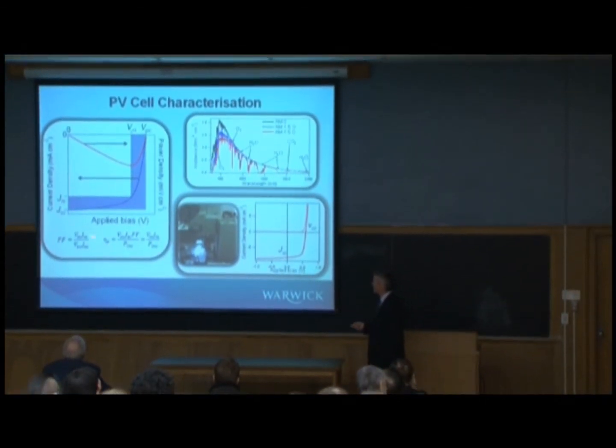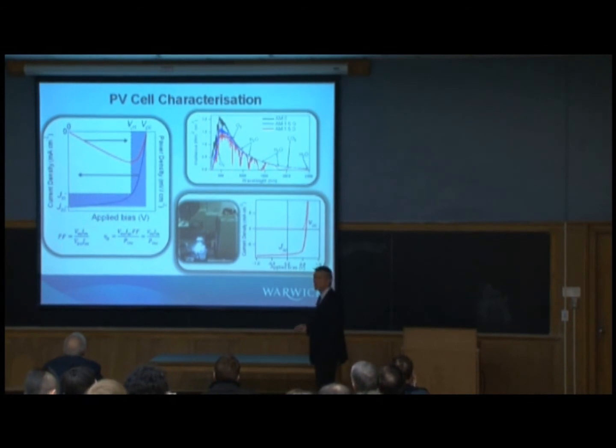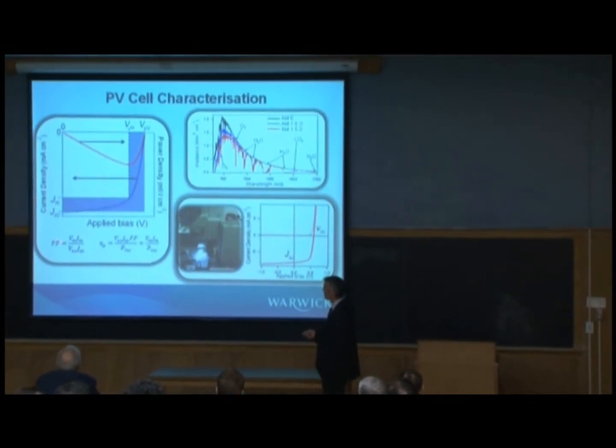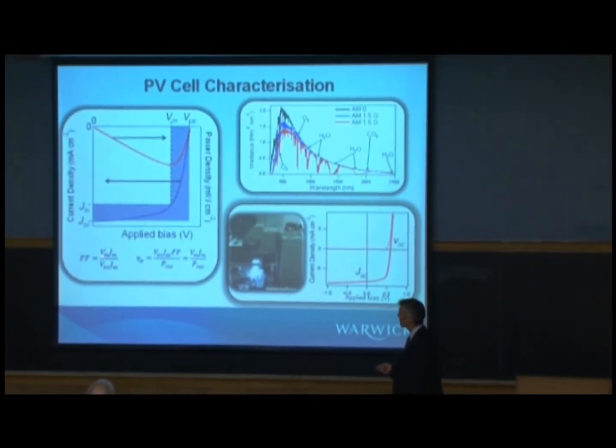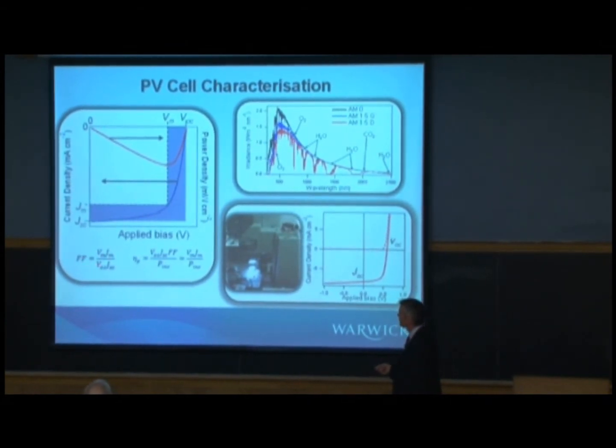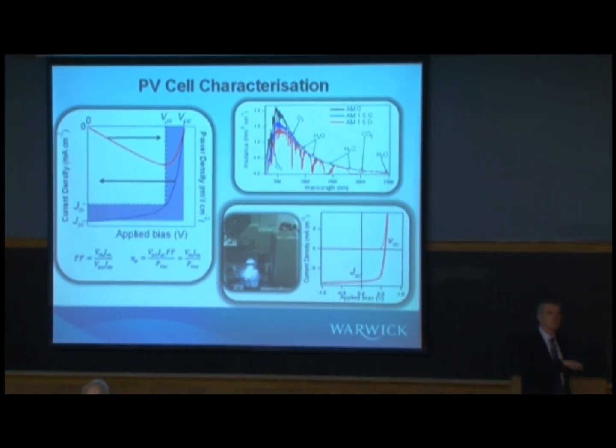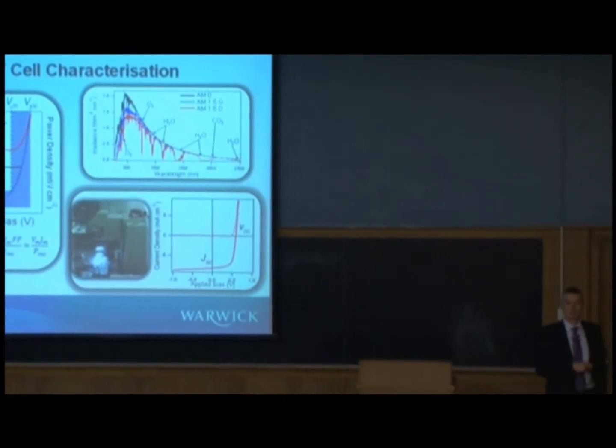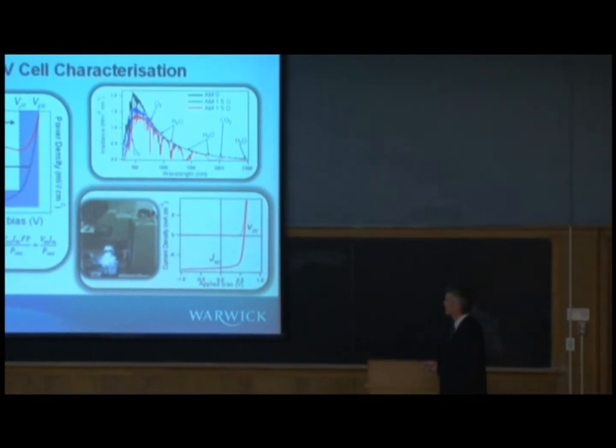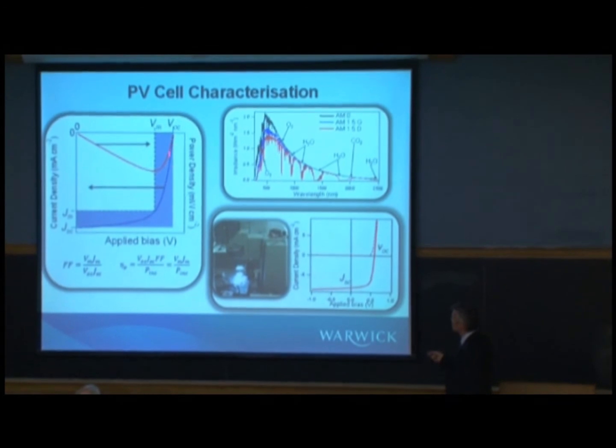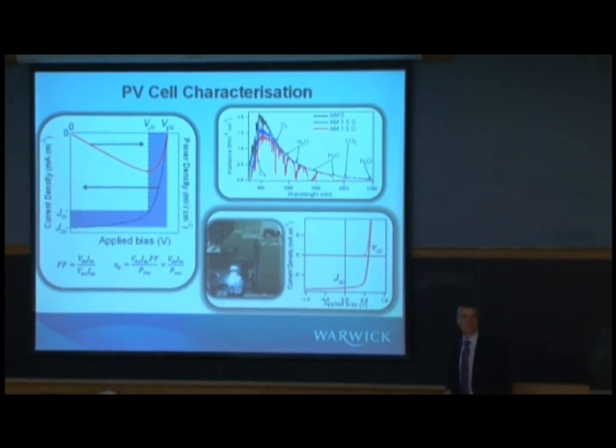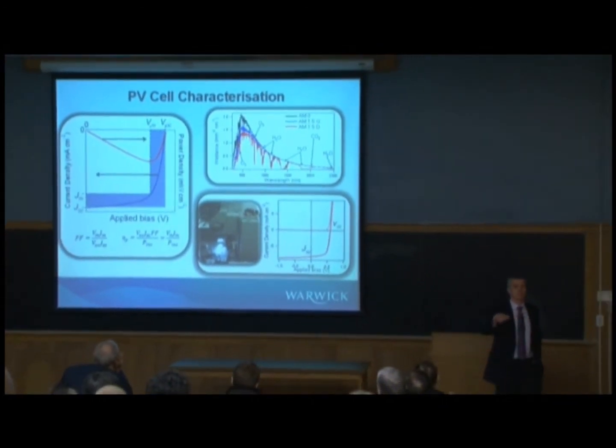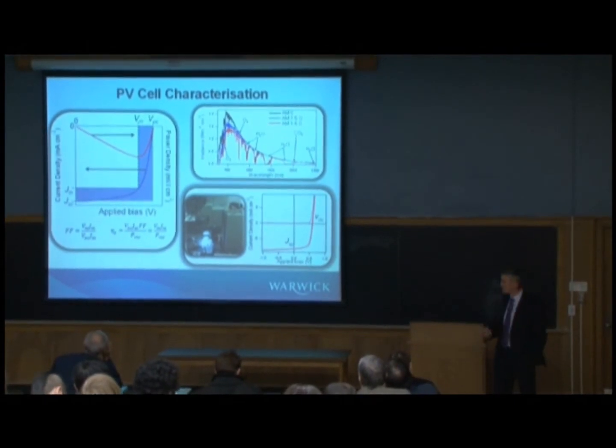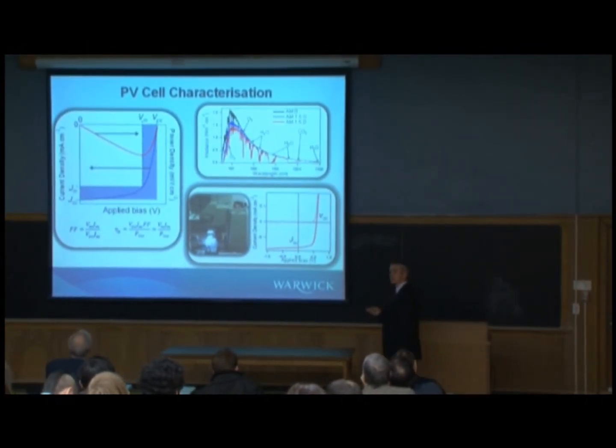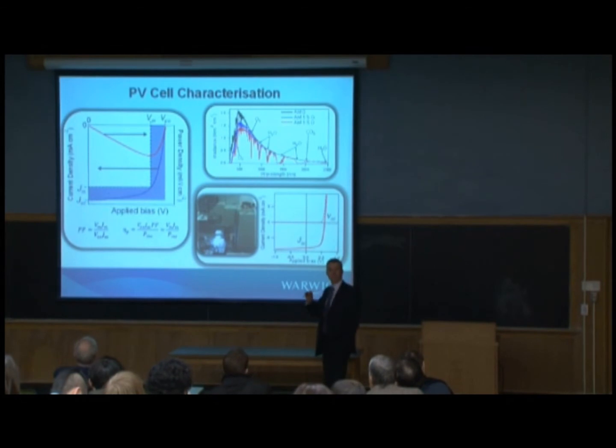And we can define something known as the fill factor, which is the ratio of the maximum power defined by Vm and Jm divided by the power defined by the open circuit voltage and the short circuit current. Basically, the squarer the JV curve is, the higher the fill factor. Ultimately, you would like a fill factor of 1, but in reality, fill factors for organic cells are of the order of about 0.5, 0.6, at best 0.7.